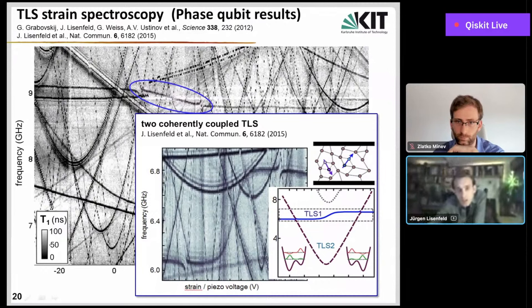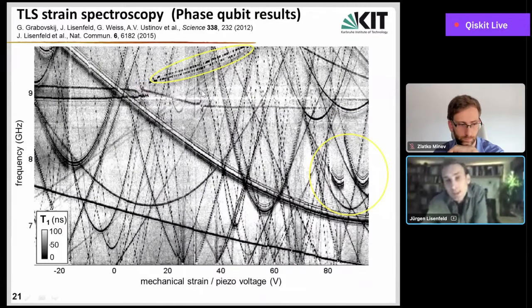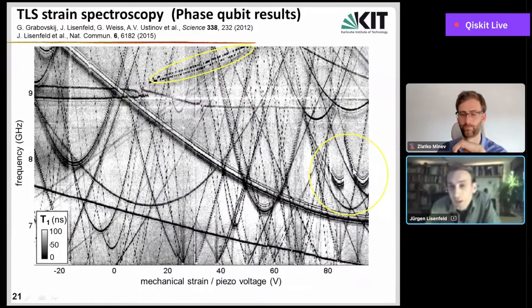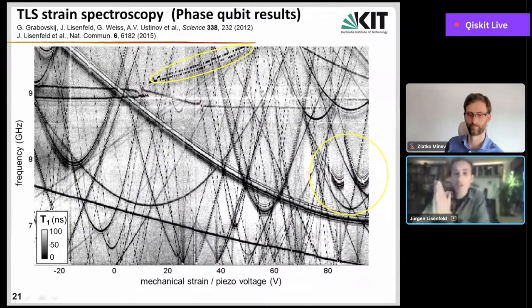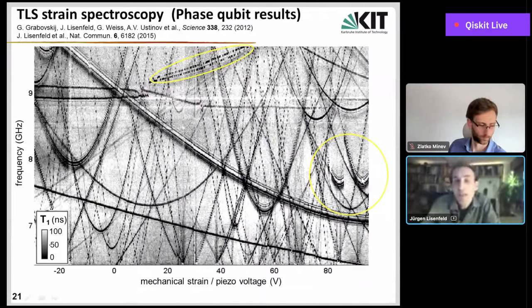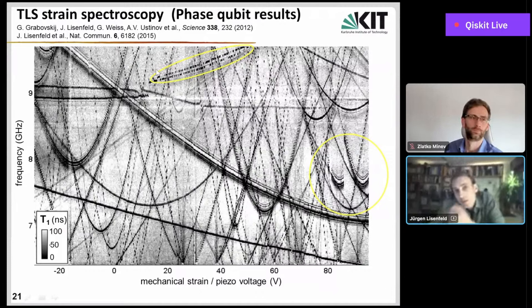And these are other anomalies. For example, here was one defect which started to develop its hyperbola, and then suddenly it decided to jump to another asymmetry energy. So it jumped up here and started again here. So there are random discrete fluctuations of the asymmetry energy of some defects. And also you can see this one here, where the resonance frequency of one defect actually shows telegraphic switching as a function of time. And now this is also a very important mechanism.